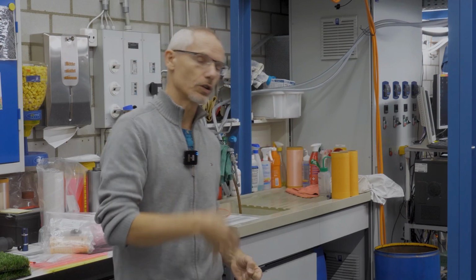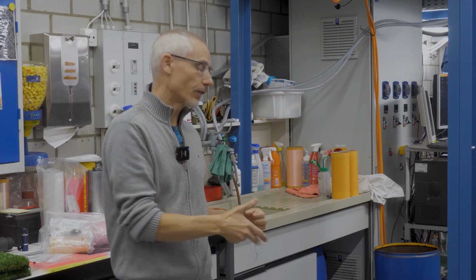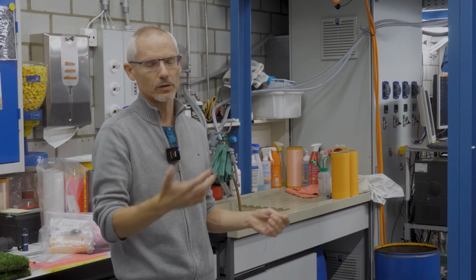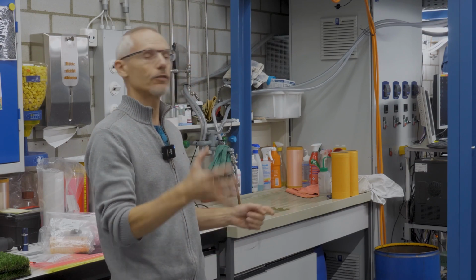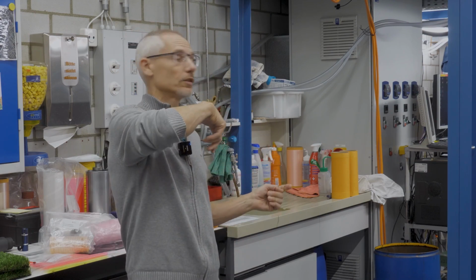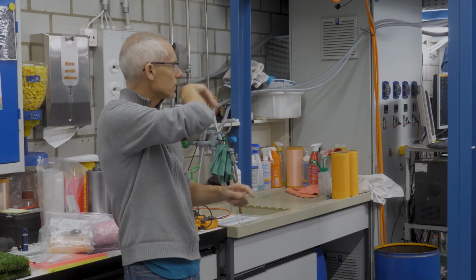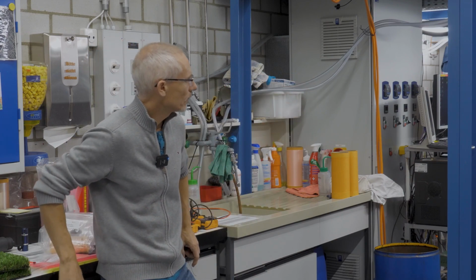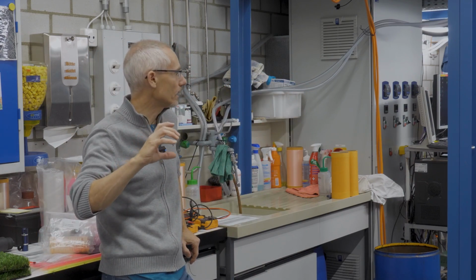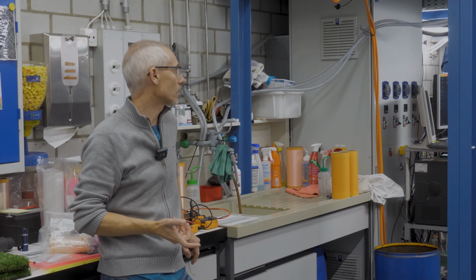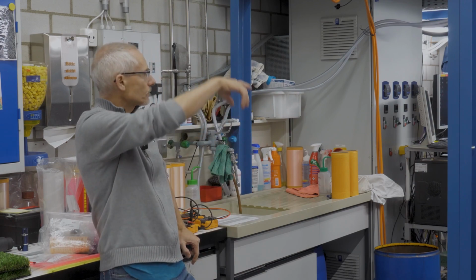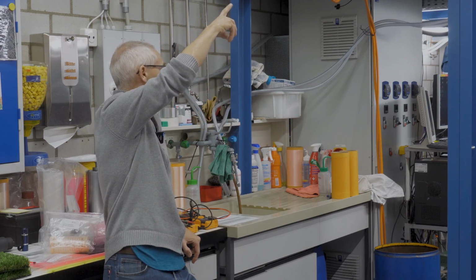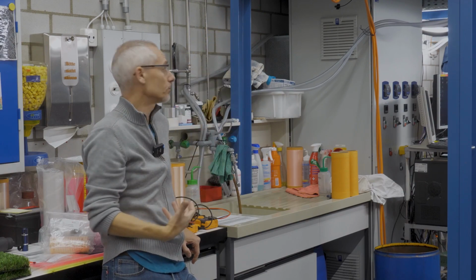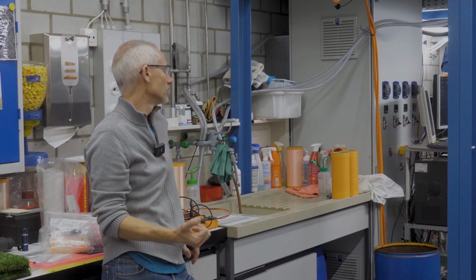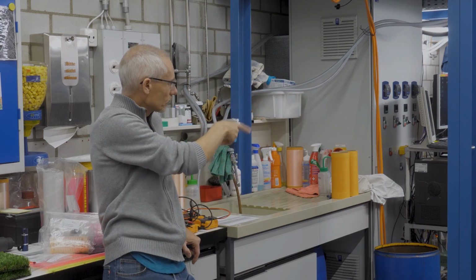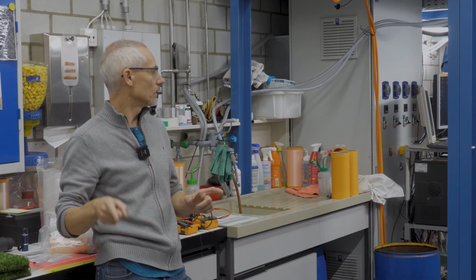To achieve this drawing in an online process, because in the end such a fiber is produced at speeds from 1,000 to 4,000 meters a minute, we have to do this drawing online during production. And for that, when you look here, you see these shiny cylinders. They are so-called godets, heated cylinders from the inside, and they can turn at speeds of our choice. Meaning, when we go from the spinneret first through a so-called quenching chamber, where we cool the polymer with cold air, then it solidifies, and then we start to draw it,